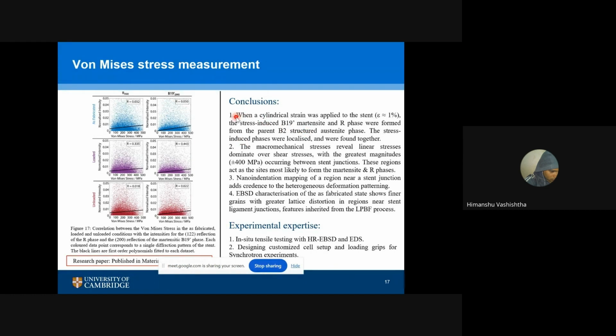When you are applying a cylindrical strain, let's say roughly 1%, two phases have popped up - B19 and R phase. And when you're applying the stresses, roughly 400 megapascals of stress has been generated close to the stents. That's a pretty huge amount, and that's most likely a precursor to form the martensite in R phase.